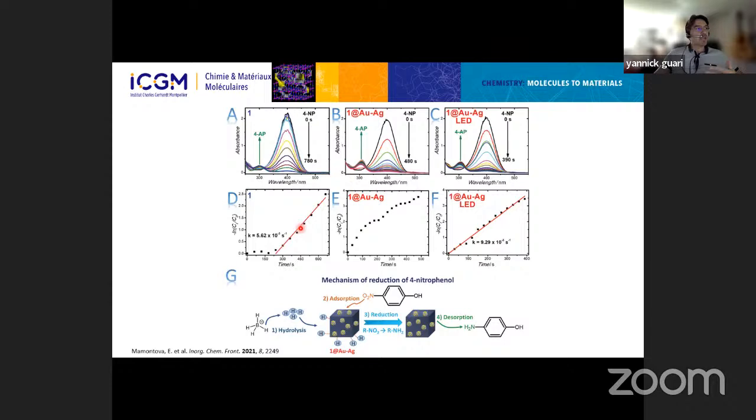This induction time can indeed be suppressed by adding hydrogen in the solution before adding the borohydride and 4-para-nitrophenol. However, in both cases, with or without hydrogen, it takes 13 minutes for completion of the reduction of 4-para-nitrophenol in our conditions. When adding the silver-gold alloy nanoparticles into the Prussian blue analog nanoparticles, there is a clear boost of the catalyst performance due to the beneficial interplay, with a reaction which is completed in only 8 minutes.